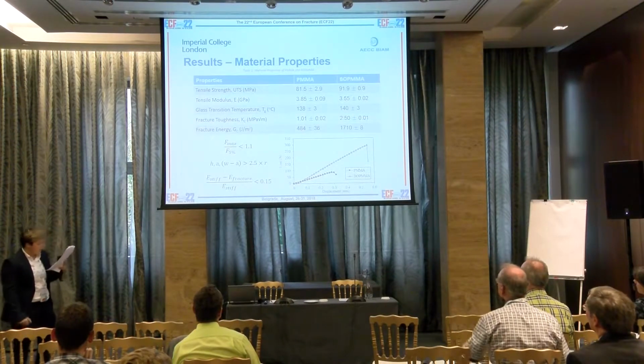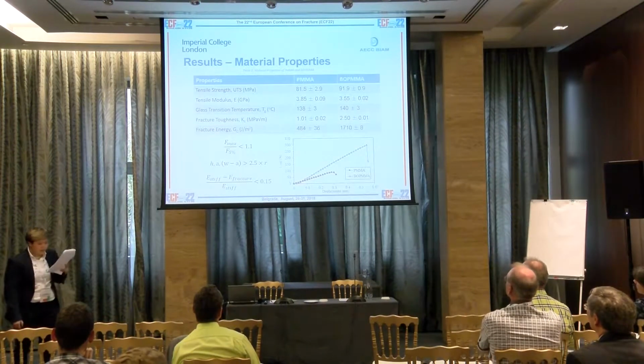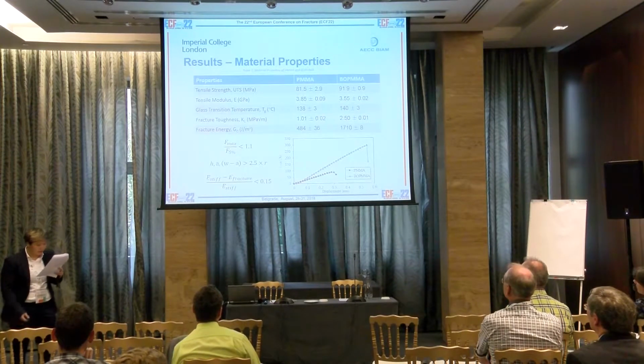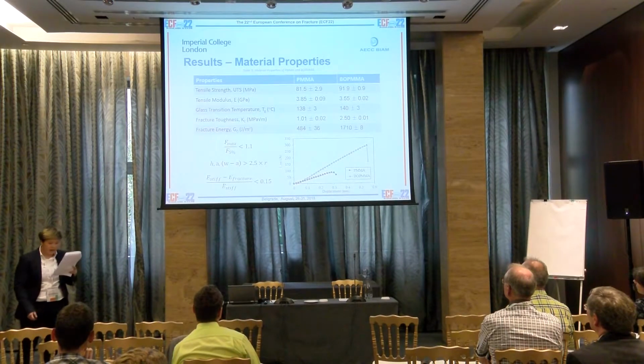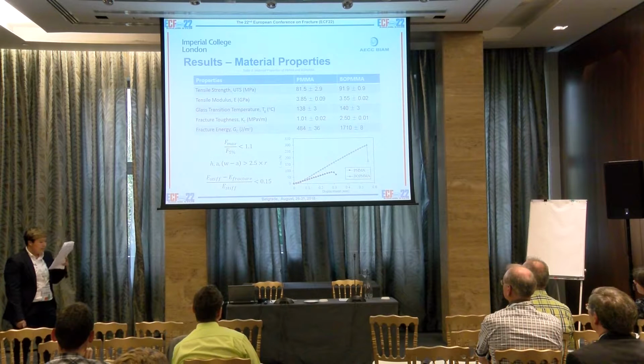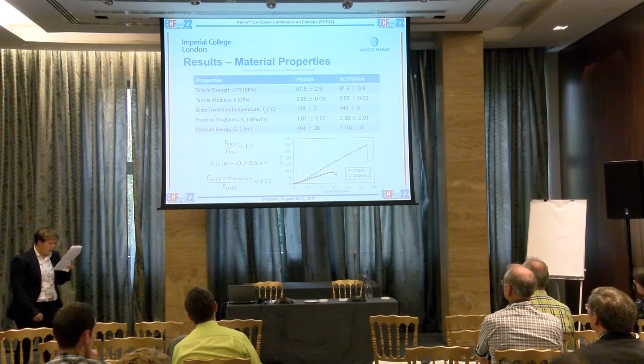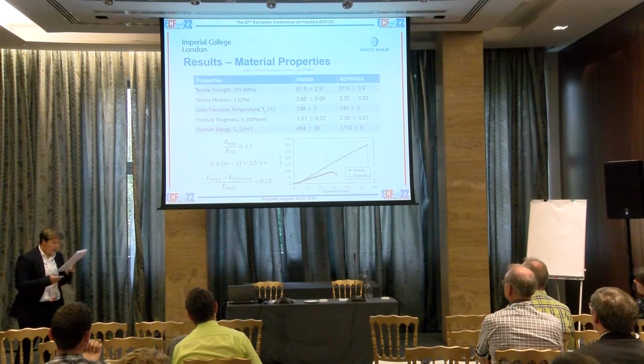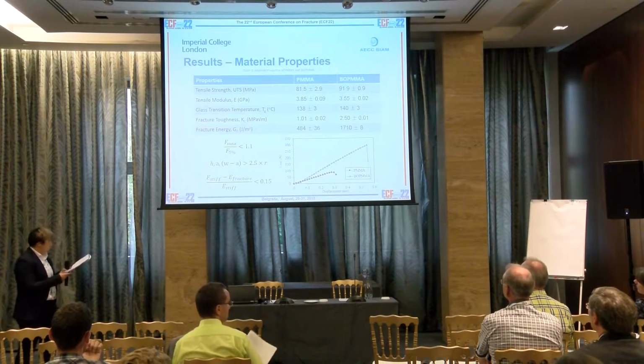The biaxial orientation has greatly improved the material fracture properties from its amorphous form. The increase in tensile strength from amorphous to biaxial PMMA is due to the increase in chain alignment in the direction of stretch. The decrease in tensile modulus after the biaxial stretching process can be explained by the high ductility in the biaxial materials. In other words, at a given stress, the BOPMMA can withstand a higher degree of deformation, hence experiences a higher strain compared to the amorphous PMMA.